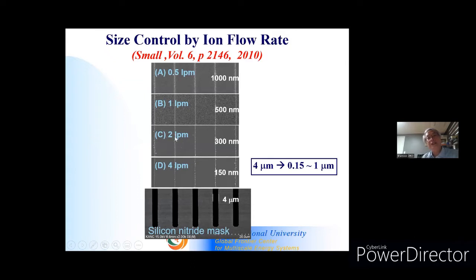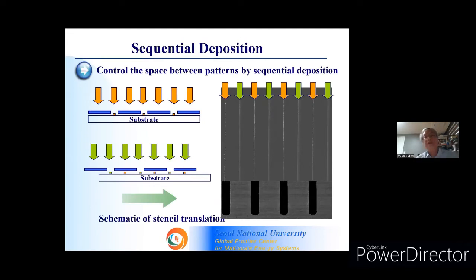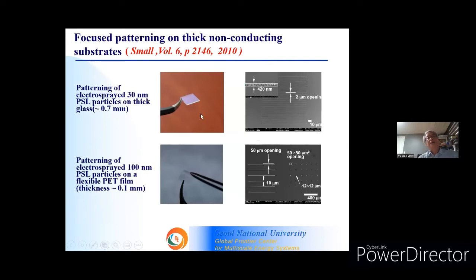As we increase ion flow rate, you can focus this charged aerosol down to 150 nanometers at atmospheric condition. This mask concept is very useful since you can translate the mask after one deposition, and another deposition is possible. It's a sequential deposition, so you can increase density of nanoparticle patterns on the same substrate. This focusing mask concept is also found to be applicable on thick glass or on a flexible PET film.